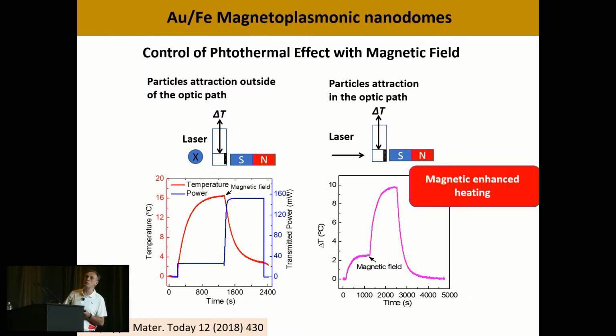If we put a magnet in such a way that the particles are pulled away from the optical path, that's the experiment here. You see that when the particles are in the optical path, the power that goes through is relatively small, and the temperature is high. This is the normal experiment without the magnet. Then we put the magnet that pulls the particles away from the optical path. The intensity going through increases because there are no particles absorbing light, and the temperature goes down.